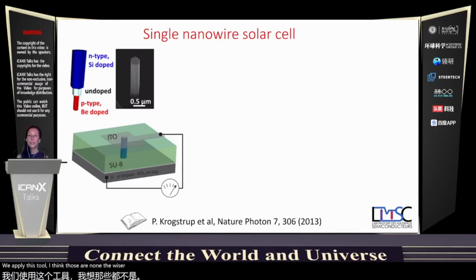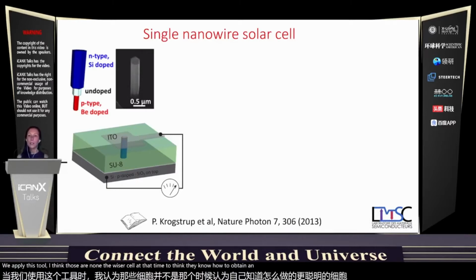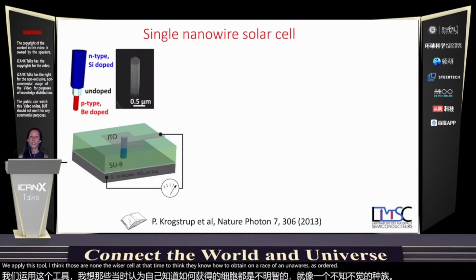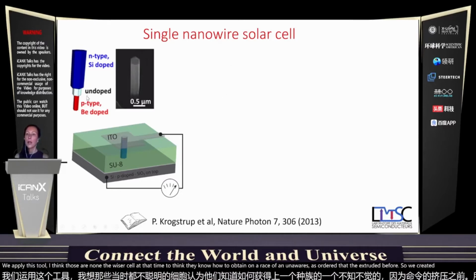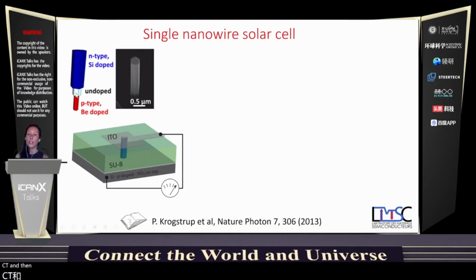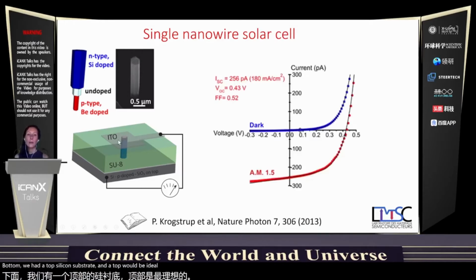At that time, we still didn't know how to obtain arrays of nanowires as ordered as I just showed you before. So we created a P-type beryllium doped core, and then an intrinsic shell, and again an N-type shell. And we then make a single nanowire device in which the bottom contact would be a very highly doped silicon substrate, and the top would be ITO. We then measure the current voltage characteristics, and you see here the characteristics in the dark and under one sun.